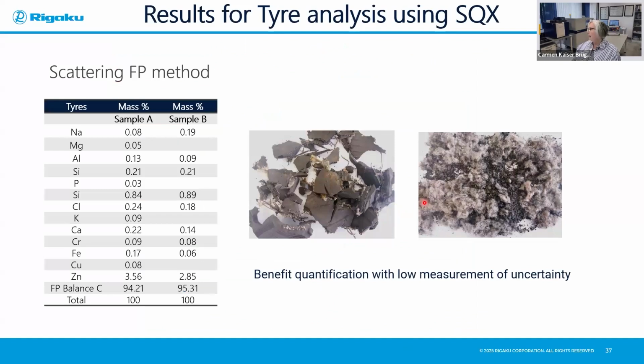If we look now at the analysis of a tire, of course this is an example of a tire that's been shredded and cut, and we can see we have a very heterogeneous sample. So how do we make the heterogeneous sample into a homogeneous sample? Well, there are different types of equipment that are available to mill the sample using cryogenic milling. And this is exactly what we've done here. We've shredded this and we've gone to another step, which involves cryogenic milling. We make the material hard and brittle by treating it with liquid nitrogen, and we are able to then produce this kind of sample, which still looks heterogeneous, but it is completely pulverized.